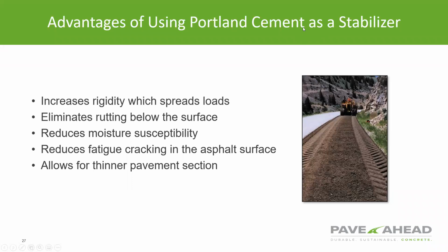Portland cement is known in the industry as the universal stabilizer because it works with so many different soil classifications. But the benefits include spreading the load, as we just looked at in that graphic, which eliminates the rutting below the surface. It reduces moisture susceptibility, reduces fatigue cracking in the asphalt surface, and it could allow for a thinner pavement section. And what I recommend to engineers is they don't reduce the asphalt pavement section, but rather leave it as is and enjoy a longer pavement life.